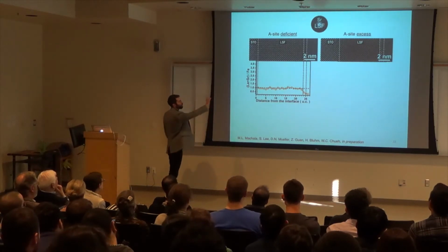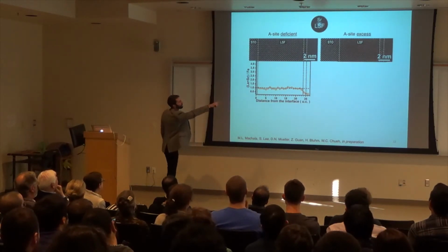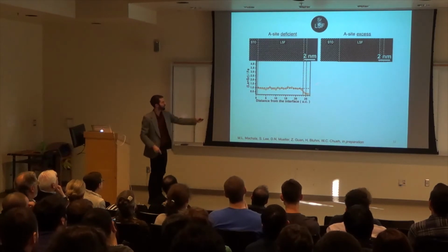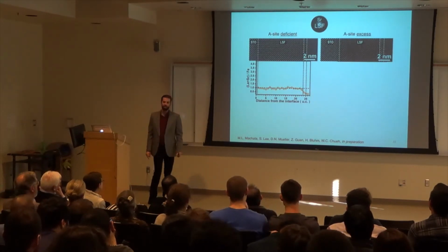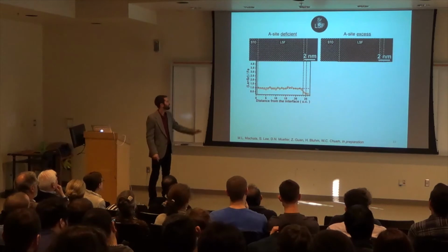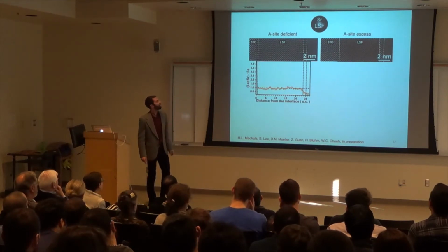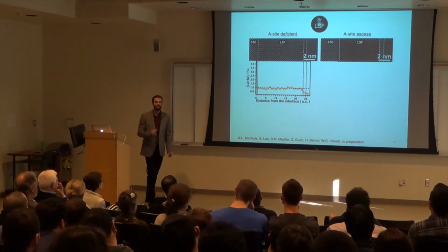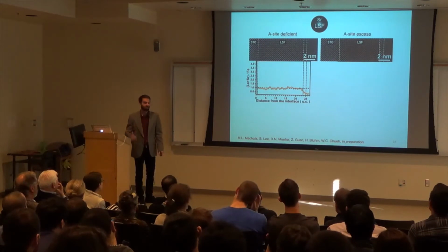So as we move from the bulk, which is relatively constant, out to the surface, you can see that there's a big drop right here, right at that cation double layer. And what that tells us is that it's going to 0. That means that the termination layer is mostly B site, iron.